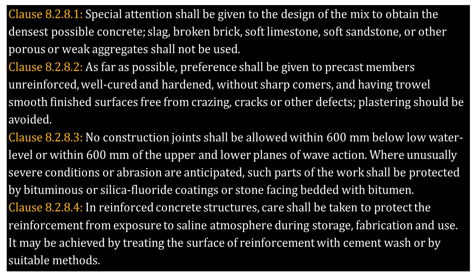Clause 8.2.8.4. In reinforced concrete structures, care shall be taken to protect the reinforcement from exposure to saline atmosphere during storage, fabrication, and use. It may be achieved by treating the surface of reinforcement with cement wash or by suitable methods.